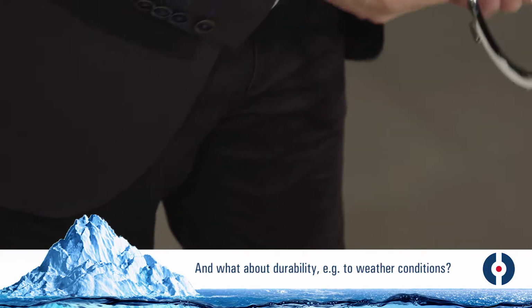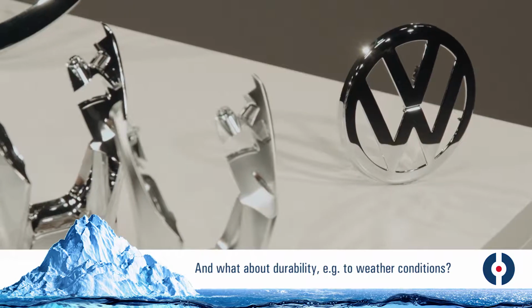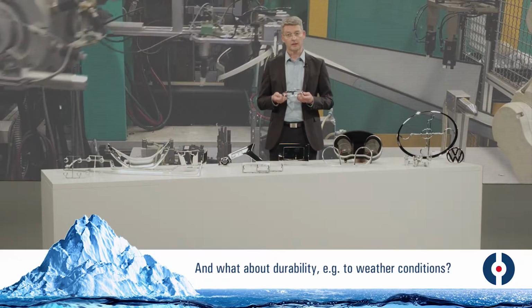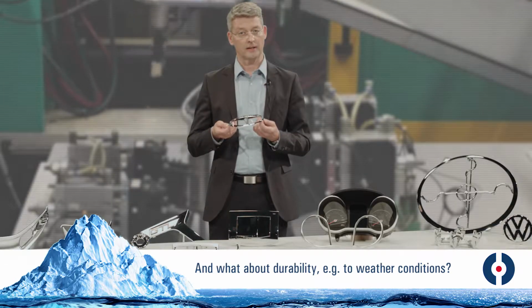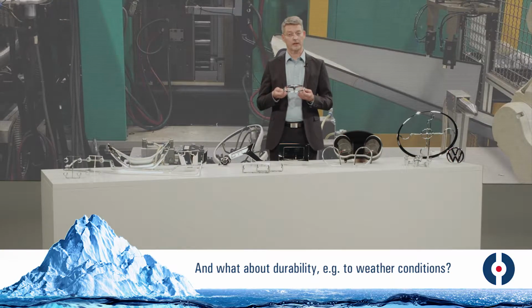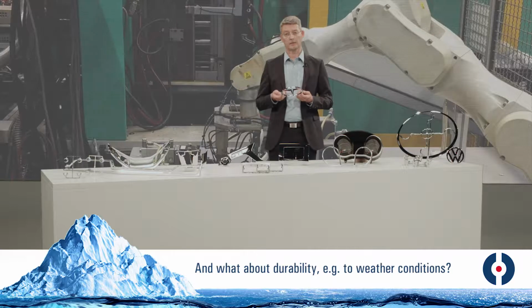The resistance of electroplated components can be compared with that of real metal components. We apply a metal layer that is firmly anchored in our plastic parts. Caverns are created during production, and metal is stored in these caverns. So we have an interlocking connection. As a result, scratch resistance and peel resistance are just as high as for real metal components.